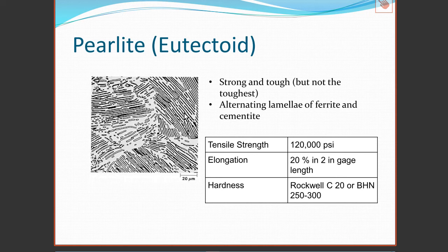Almost the perfect combination for making a tough, strong material in which dislocations within the ferrite are blocked by this hard, strong material, and the soft ferrite adds toughness. This means the material is tough, it can absorb energy, and it's strong. It's an amazing material, and it's sometimes been called a nanostructured metal-ceramic composite.